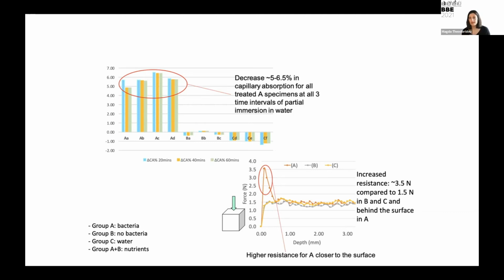And in this case, the DRMS profile showed a peak of high resistance for Group A specimens, which you can see here. And that was not the case for Group B and C. And that happened in the area closer to the treated surface of the specimens.